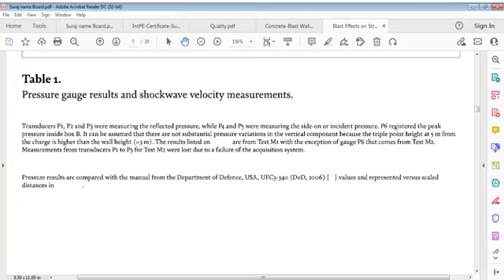It can be assumed that there are not substantial pressure variations, with a vertical component, because the triple point at 5 meters from the charge is higher than the wall height. Results are from test M1, with the exception of gauge P6, which comes from test M2. Measurements from transducers P1 to P5 for test M2 were lost due to a failure in equipment.